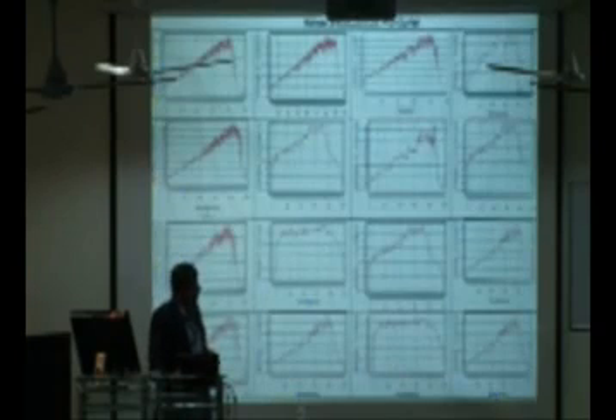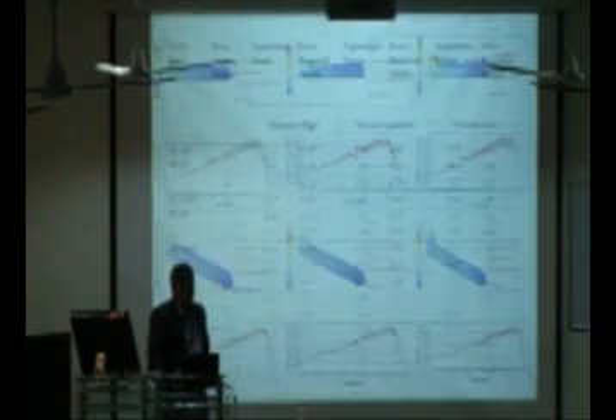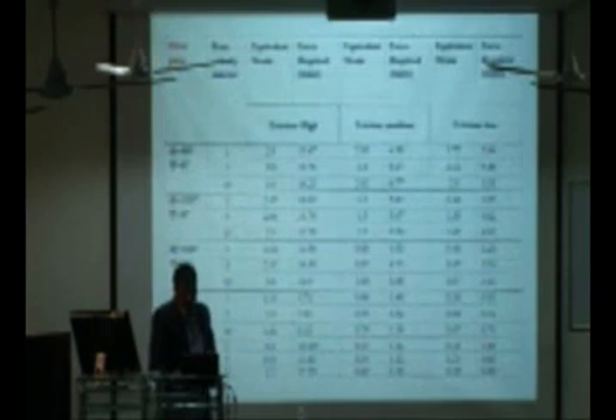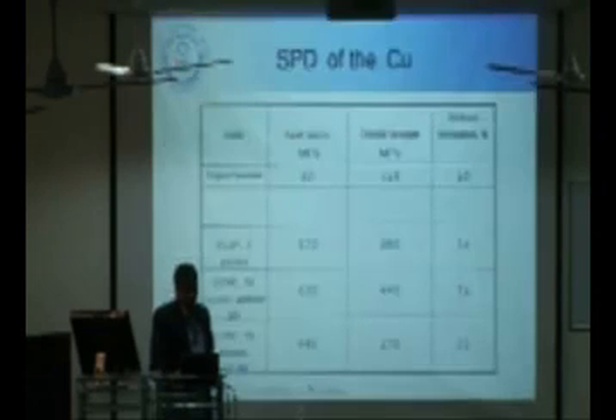There are two aspects of this work. One aspect was what the best process parameters should be. For that we have done a good amount of FEM modeling for all different angles and all different process parameters like velocity, friction and temperature. These are the results from which we are able to conclude something. These are the results for different phi, different psi, friction and velocity, and we have done this for 4 passes.